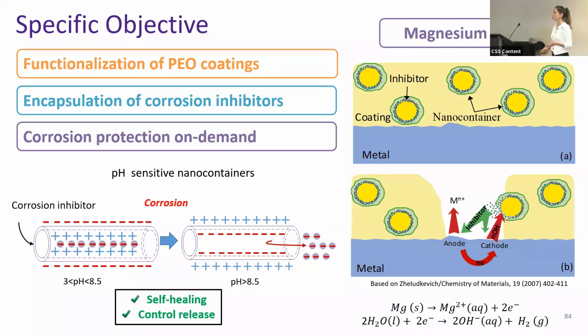So the specific objective of this work is to achieve the active functionalization of plasma electrolytic oxidation coatings by incorporating corrosion inhibitors encapsulated into pH-sensitive nanocontainers. Why is it interesting to use a pH-based trigger? Well, because corrosion phenomena is intimately related to pH changes.